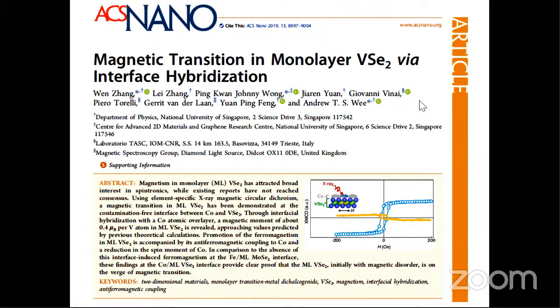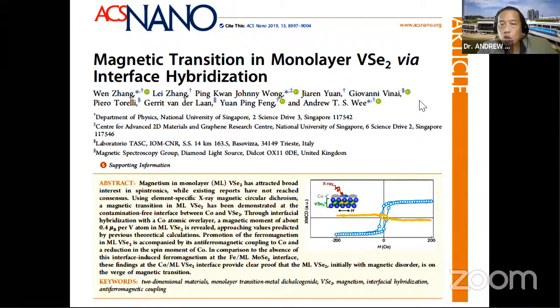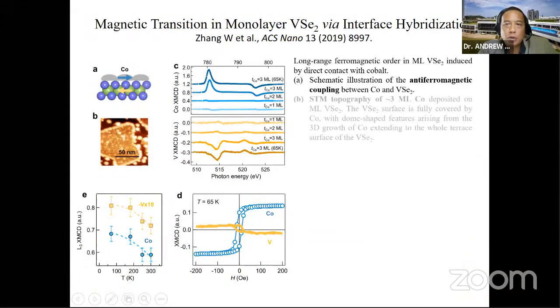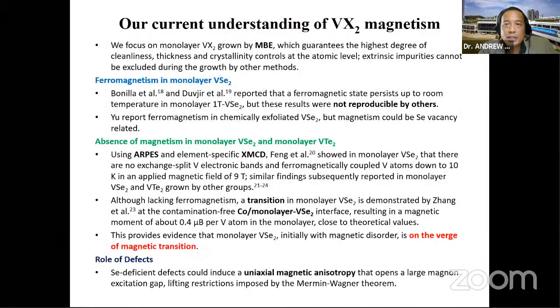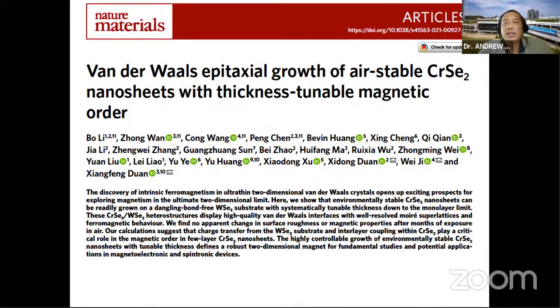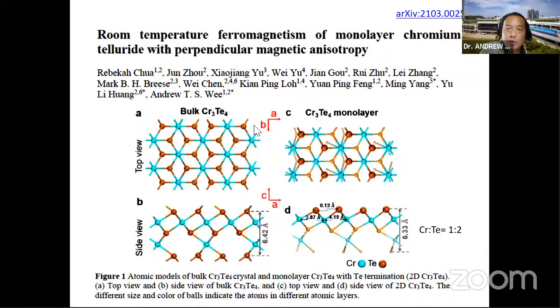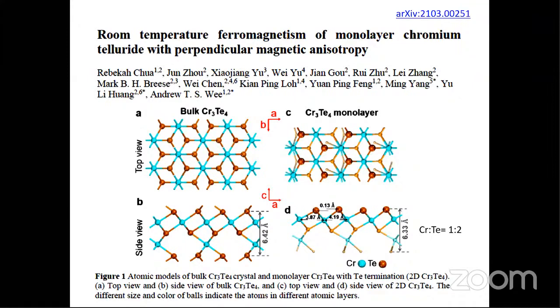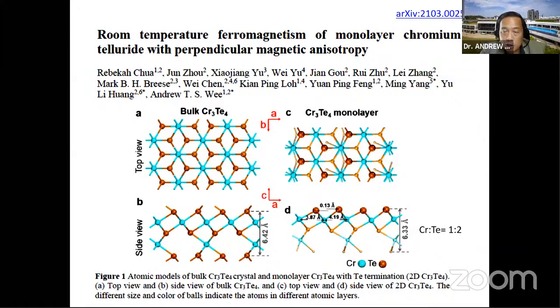Okay, thank you. The next question is, the chromium increase in the monolayer also shows some specific changes. I suppose this is referring to the last work, the chromium increase in the monolayer. Okay. Now, I did mention to you that from XPS, the stoichiometry actually does change, and we are suggesting that the ratio changes from 3:4 to 1:2 here. So in a sense, the chromium does increase, but actually it's because the tellurium decreases. The monolayer forms by annealing to higher temperature, and with annealing, tellurium being the more volatile element would preferentially dissolve. So this is our reason for why we believe that the chromium increases.